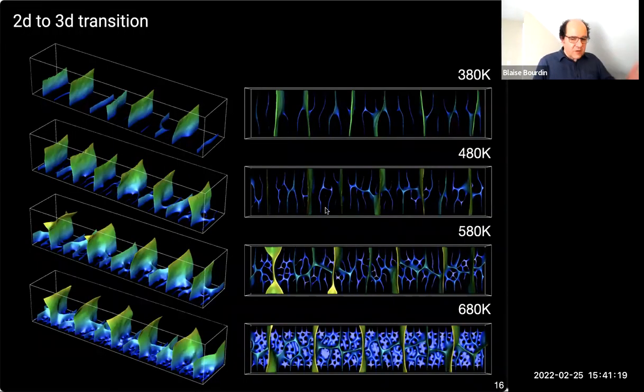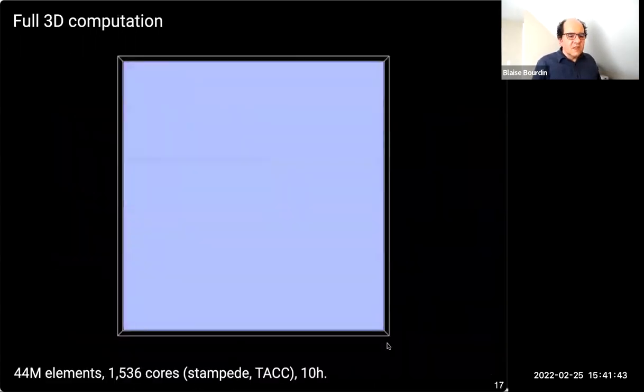And what you see is that if you increase the magnitude of the field, you would go from a simple network of transverse cracks, still with this selection principle, where some cracks stop early and some cracks continue growing, to a situation where you have that, but you also have this complicated three-dimensional pattern. And then you can go even smaller. You can try to look at an even smaller scale, what happens next to the boundary. So that's a 3D computation. Think of this as being inside the material and seeing the crack pattern growing towards you.